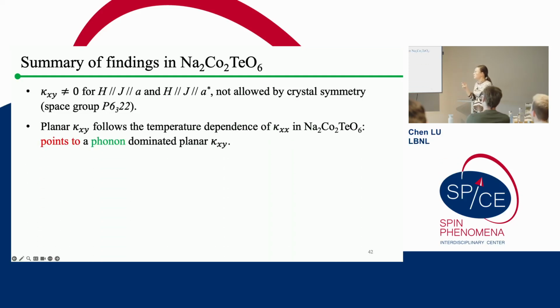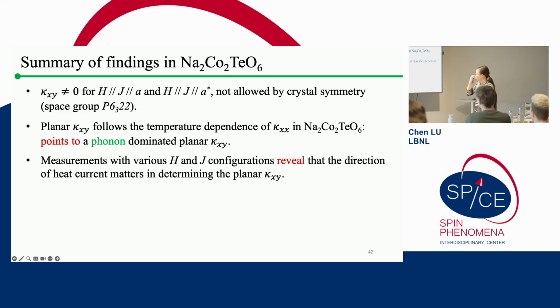The second thing is, the reason why we point to it being a phonon planar thermal Hall effect is because the thermal Hall conductivity follows exactly the same temperature dependence as the phonon-dominated thermal conductivity. This is a very important argument for that mechanism. After that, we tried planar thermal Hall effect measurements with different types of configuration, and found that you need to know the exact correspondence between the direction of the field and the current to determine how large the magnitude of your planar thermal Hall effect is.